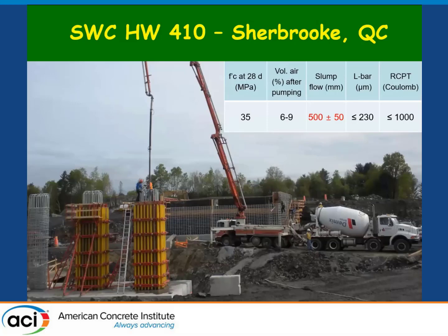In our industrial chair, we worked quite a bit on developing this, and then very close to our campus in Sherbrooke at the time, there was a highway being constructed by the DOT, who was a partner, and decided to use this superworkable concrete to construct some bridge elements. And you can see over here some piers of the bridges. These are the specified properties, so it's 5,000 PSI, air entrainment. These are the air contents after pumping, and the slump flow range is 20 plus or minus 2 inches, and adequate spacing factor and low RCPT.